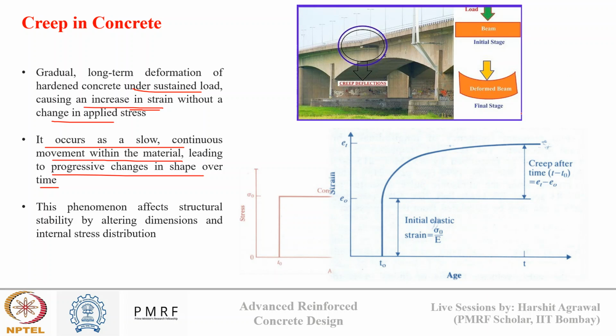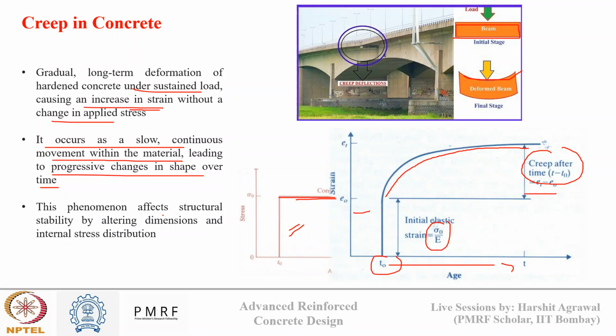It starts to show vertical deflection, or creep deflection. Here, this is the beam, and over time, due to sustained loading, it has deformed, deflected from the middle, and that is due to creep. You can understand the same thing from this diagram also. Here we have a constantly applied stress acting on a system, and under this constant stress sigma naught, after an initial elastic strain generated due to the modulus of elasticity of the material, over time, if we keep the stress constant, you will see more strain generating in the concrete due to creep. So the strain that increases after time t naught till time t is due to creep, and this phenomenon affects structural stability by altering the dimensions and the internal stress distribution.